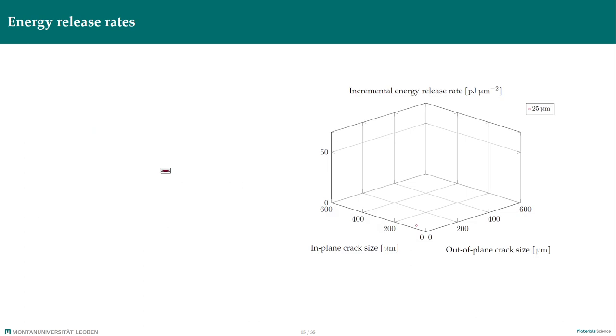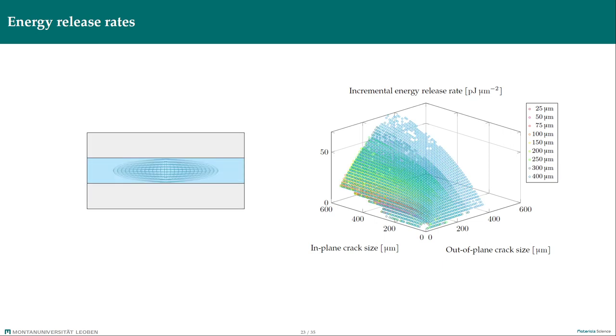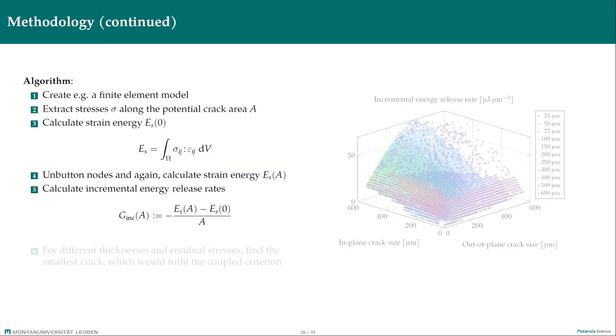The thicker the layer, the more crack sizes can be introduced to it. So on the left side, you see only illustrative image, which shows us how for different crack sizes and aspect ratios, we calculated the energy release rate, which are shown for different thicknesses. And this is displayed with different colors on the right diagram. We calculated up to thickness of 600 microns. And we get the surface representing the incremental energy release rate.